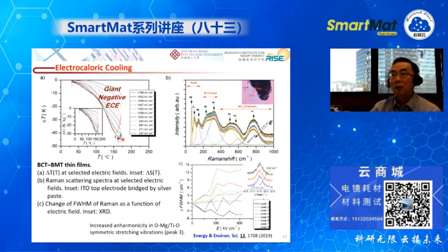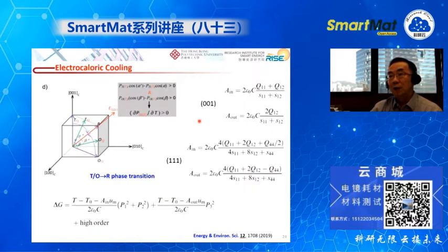And normally we know when you increase the temperature of this material, the polarization will decrease. So the electrocaloric effect will normally be positive. So why here do we get a negative electrocaloric effect? Then we use a phenomenological theory to try to explain the result. We found it is due to the field-induced phase transition.